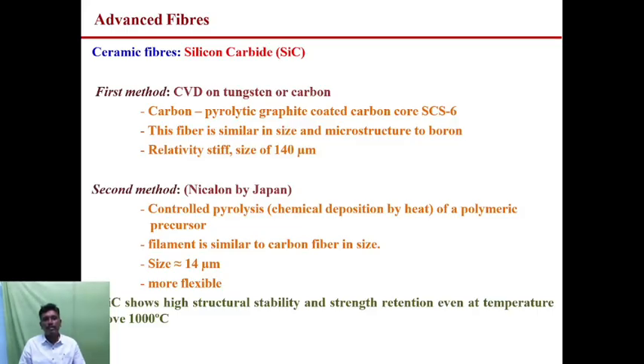Here two methods are used to synthesize silicon carbide. The first one is chemical vapor deposition on tungsten or carbon, pyrolytic graphite coated carbon core, SCS-6. This fiber is similar in size and microstructure to boron. Relatively stiff, size of 140 micrometer. In the second method, controlled pyrolysis, chemical decomposition by heat of a polymeric precursor. The filament is similar to carbon fiber in size, approximately 14 micrometer, and more flexible. Silicon carbide shows high structural stability and strength retention even at temperatures above 1000 degrees centigrade.